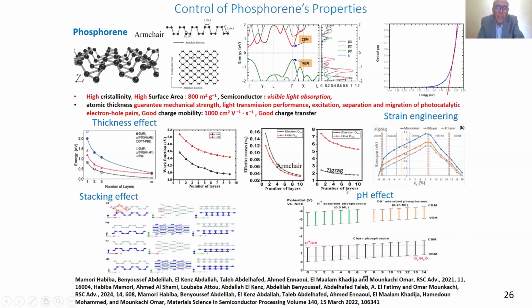For the application of this material for photocatalysis, for example, it is possible to move the alignment of the bands by controlling the acidity of the solution in which we put this material, by controlling the pH effect. And for example, in this case, for AB phosphorene, at pH equal 8, we have the possibility to have at the same time oxidation of water and a reduction of protons.